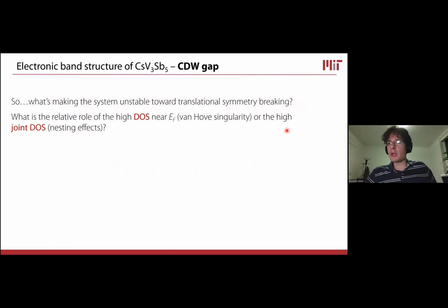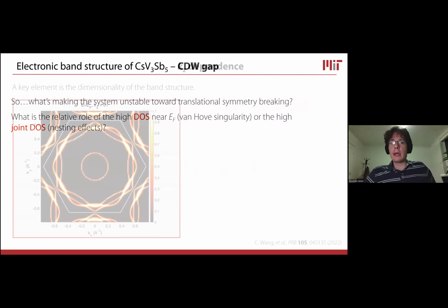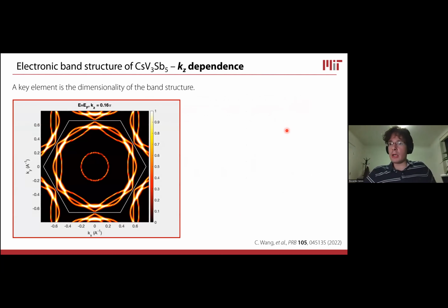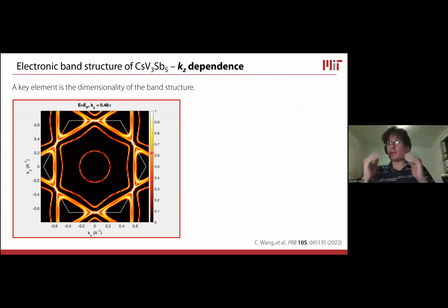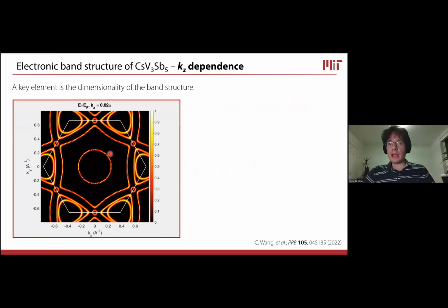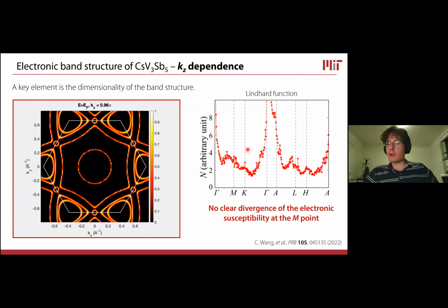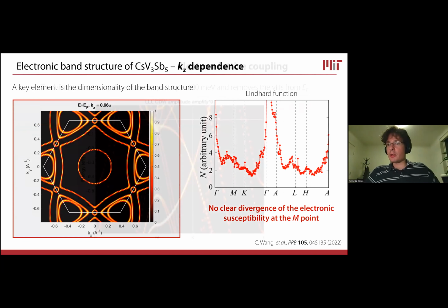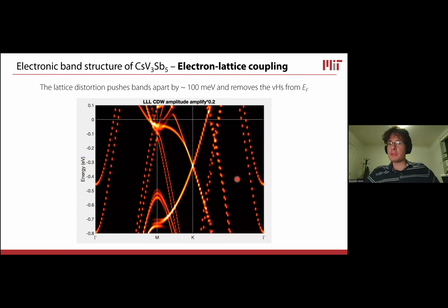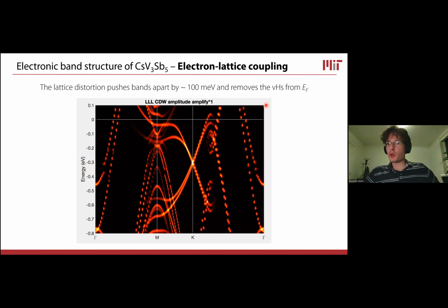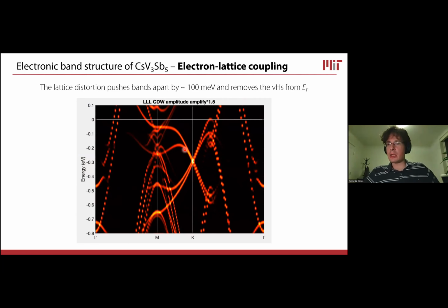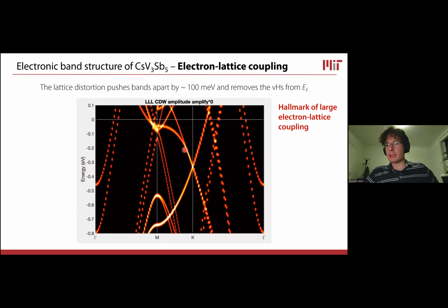So long story short, we try to disentangle the effect from the nesting from the effect due to the strong electron phonon coupling. And the conclusion is that nesting is not very strong because despite the fact that this Fermi surface looks very flat, looks like a perfect hexagon, it actually has a lot of kz dispersion, and so it becomes very warped. And so the susceptibility is not really diverging at the M point. So the nesting conditions are not very good. But if we instead simulate what the band structure does when we distort the lattice, then the renormalization to the electronic bands is massive, which suggests that there is really a very large electron lattice coupling that drives the formation of the charge density wave.